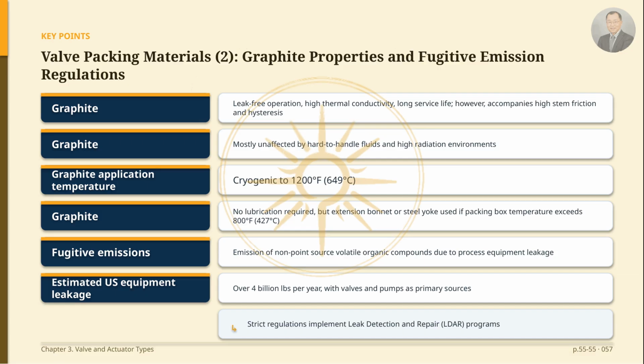I'd like to continue introducing the characteristics of graphite packing. Graphite provides leak-free operation, high thermal conductivity, and a long service life, but in exchange, it produces high stem friction and resultant hysteresis. It is virtually unaffected by most hard-to-handle fluids and high radiation environments. The operating temperature range is very wide, from cryogenic temperatures up to 1,200 degrees Fahrenheit or 649 degrees Celsius. Lubrication is not required, but if the packing box temperature exceeds 800 degrees Fahrenheit or 427 degrees Celsius, an extension bonnet or steel yoke should be used.